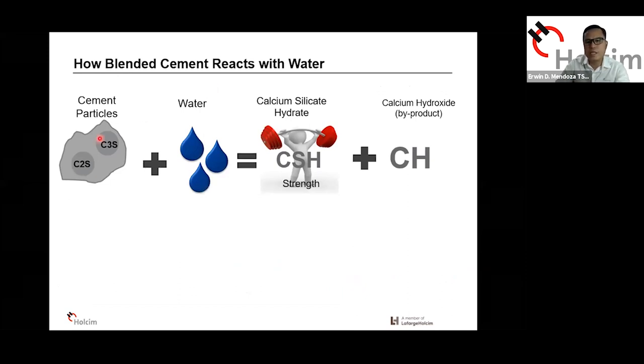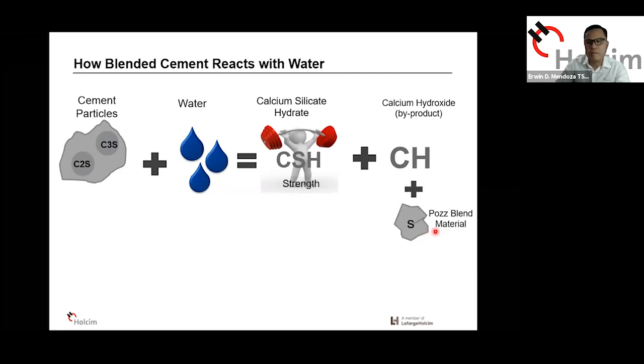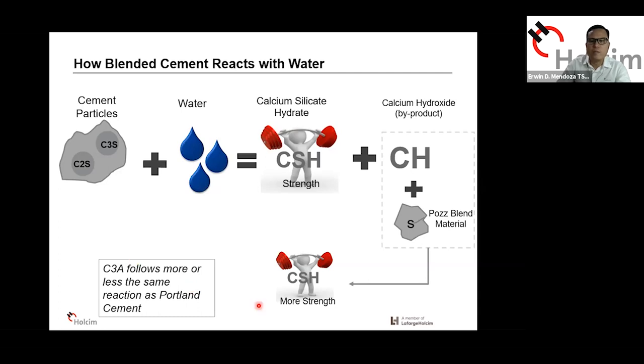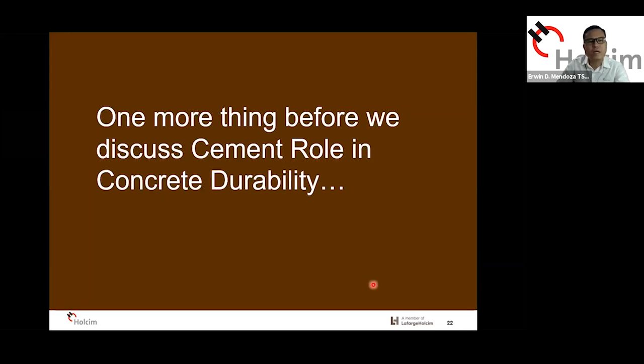For blended cement, the same hydration occurs — C3S and C2S react with water to produce CSH and calcium hydroxide. But then, this calcium hydroxide by-product reacts with the blend material — such as pozzolan, slag, or fly ash — forming more calcium silicate hydrate, giving more strength. So the blend material is not just an extender; it has a purpose in hydration. That's why pozzolan cement gains strength long-term compared to OPC — the blend material consumes and utilizes that otherwise-purposeless calcium hydroxide.